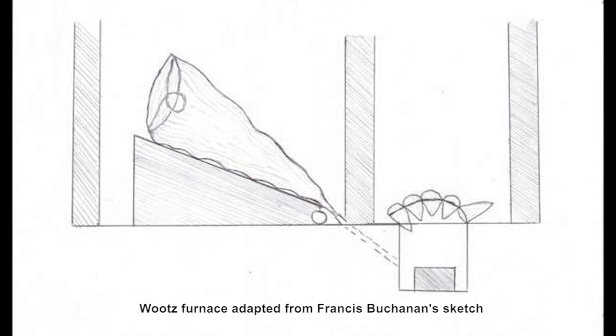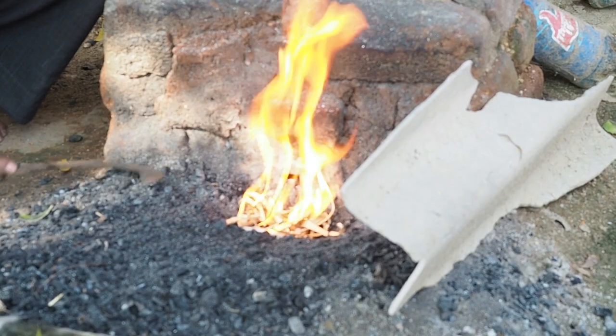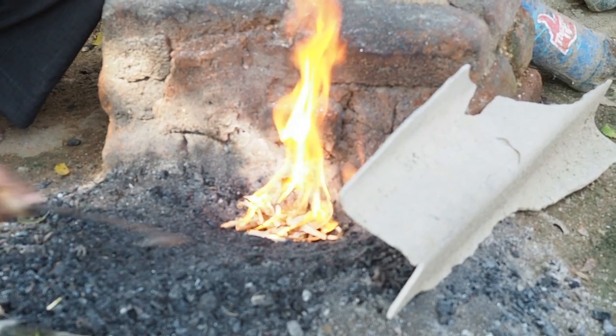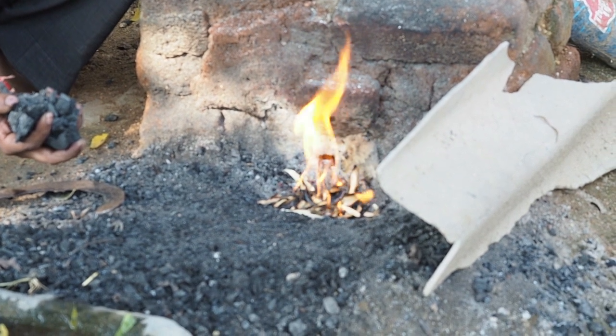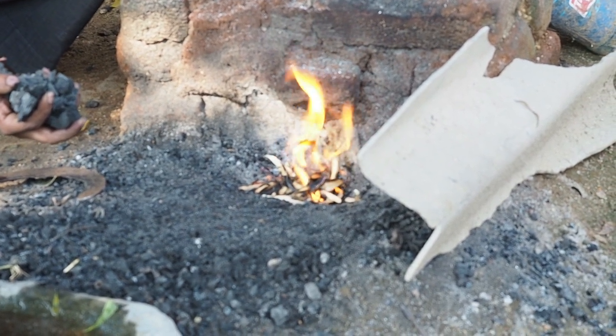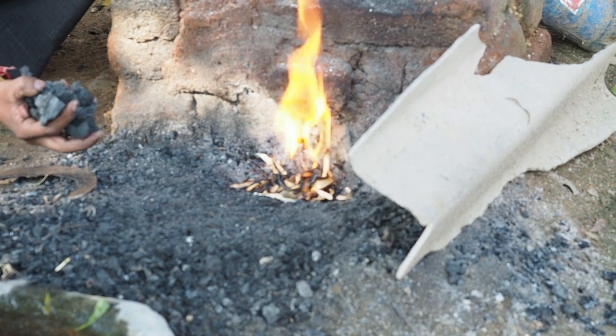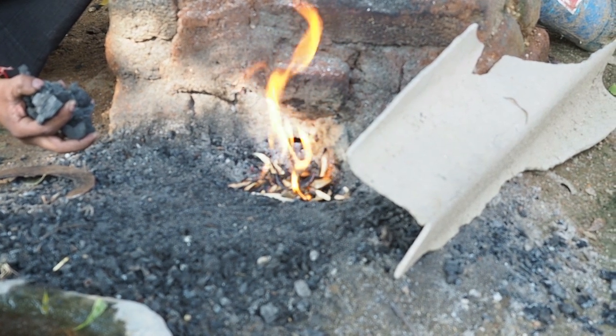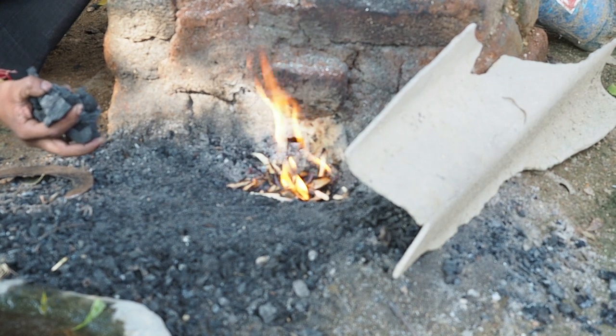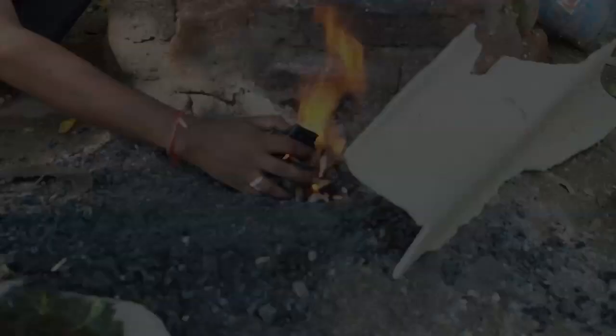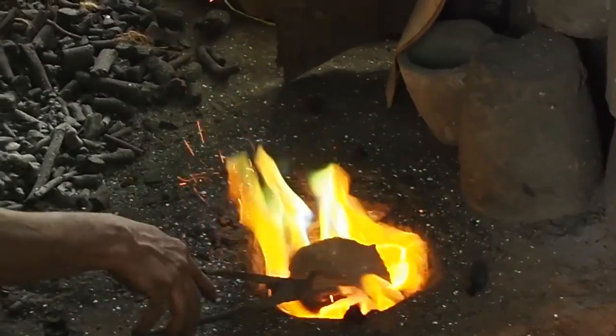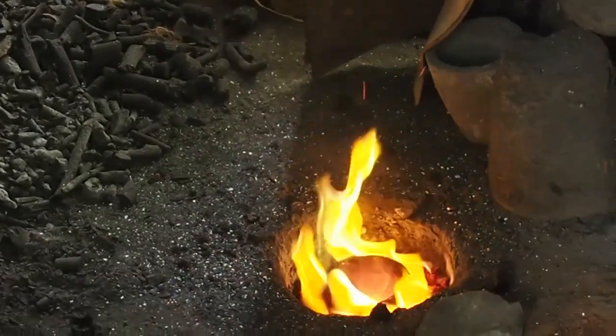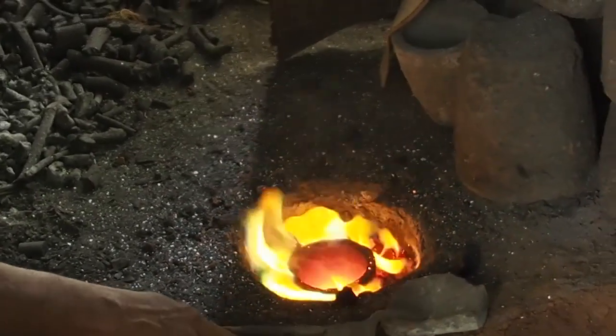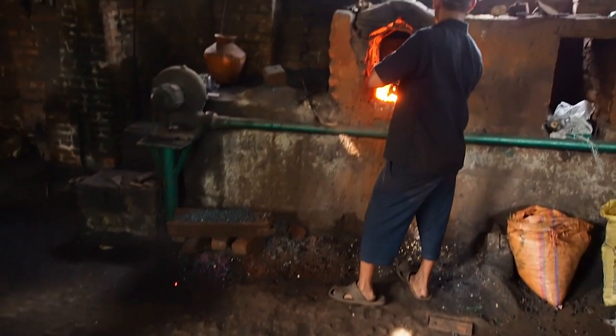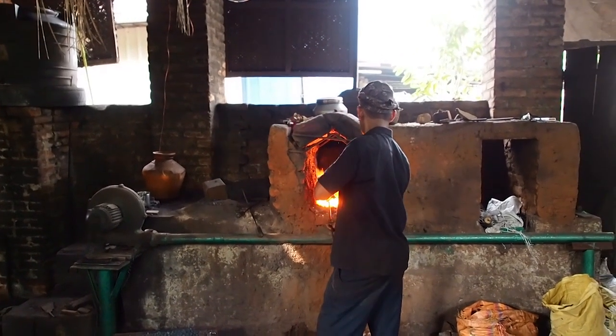Francis Buchanan, in his travels in the Karnataka region in the early 1800s, observed the making of wootz steel by carburizing low carbon iron to get a high carbon content, by packing it into crucibles with carbon-rich matter and firing under highly reducing conditions at high temperatures of at least 1200 degrees centigrade. The term Wootz is a corruption of the word ukku, which may relate to urukku, which is the word for melting in several South Indian languages, including Tamil and Malayalam.